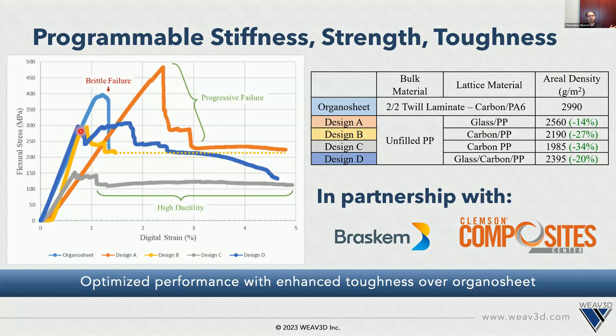It has the same initial modulus as the carbon fiber organosheet, but it has a very wide progressive failure zone due to the fact that it has both carbon fiber and glass fiber in it. So they basically fail sequentially, carbon then glass. And then it has a pretty solid plateau region afterwards. So we're getting a lot of energy absorbing capability here.